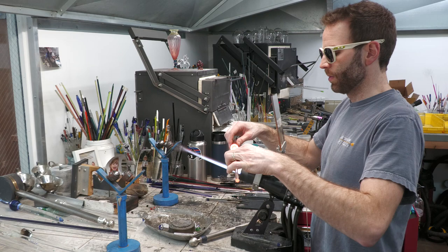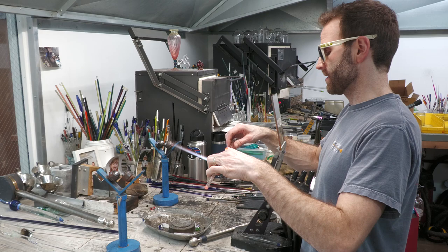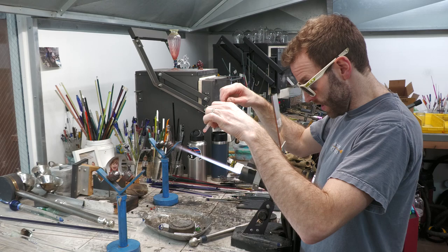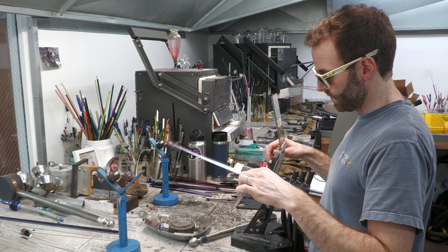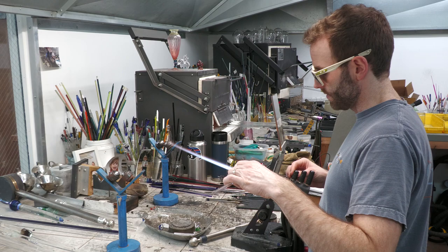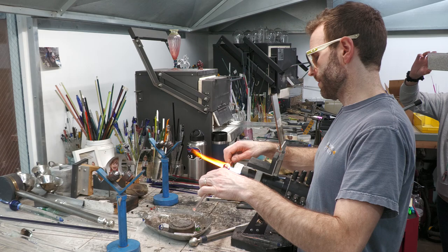It's a really common mistake to just start making a marble and suddenly realize your cone on your vortex is too big, so you have to make a bigger marble than planned and now you don't have enough clear glass for a proportionately sized lens. You can still pull it off, but I personally don't like marbles where the vortex is two-thirds of the sphere and the lens is only a third — I always shoot for 50-50. By prepping my setup with the correct rod, I know I'll have about two inches left of the 10mm rod when done.